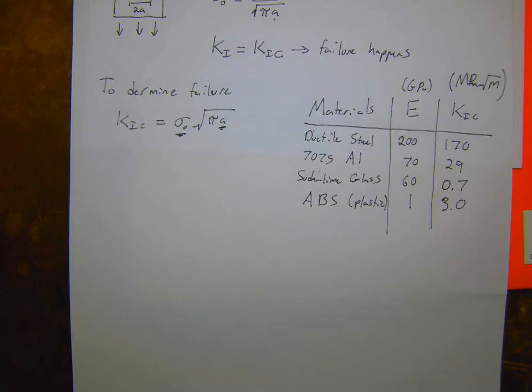So some of the toughest materials, some of the highest toughness materials are low alloy steels. Or nickel super alloys are up here. Even though low alloy steels may not be as strong as high alloy steels, they're able to absorb more energy and prevent some of the fracture processes. Yeah. Is that one just beneath the metals and alloys, the smaller? Ah, this is composites. Yeah.